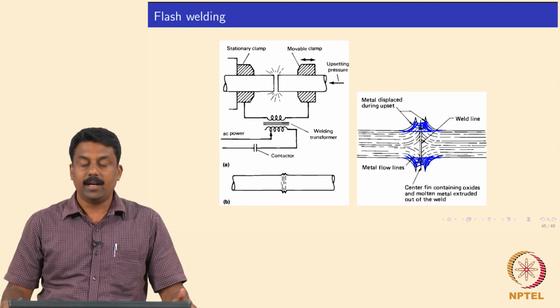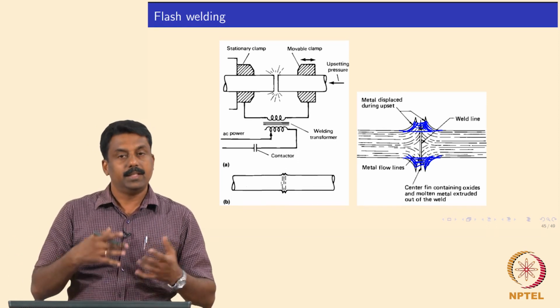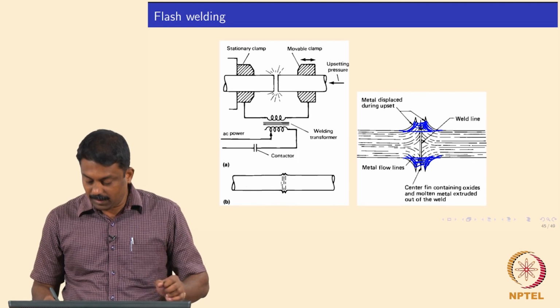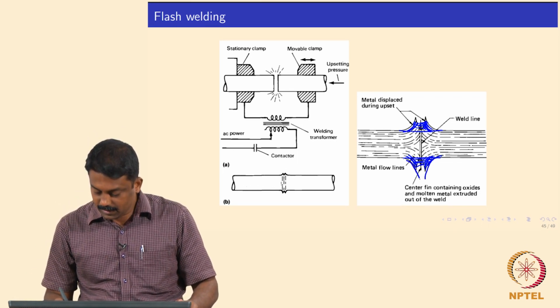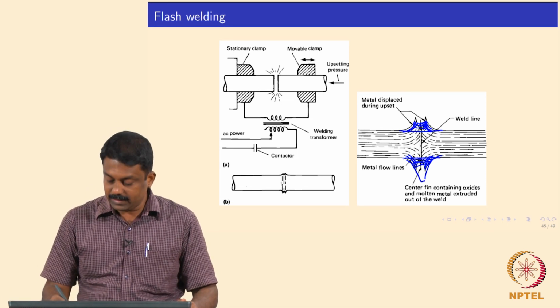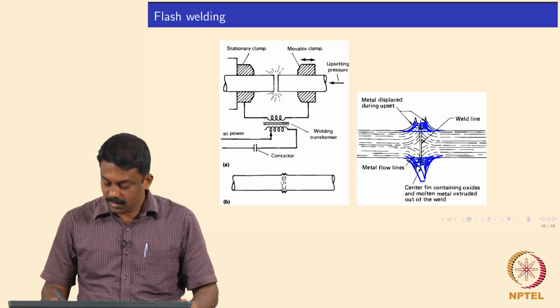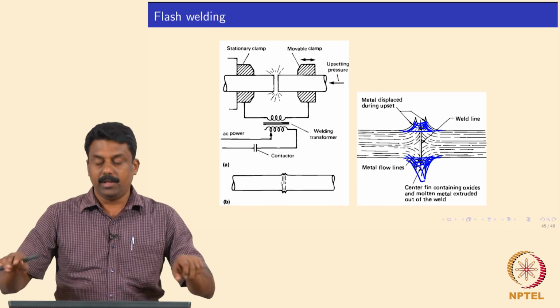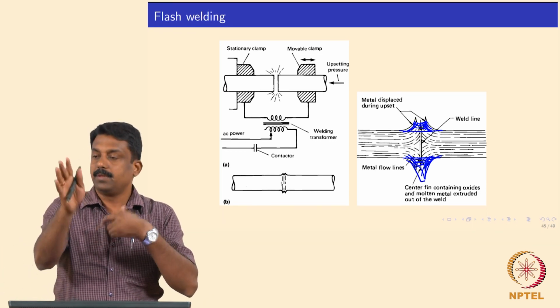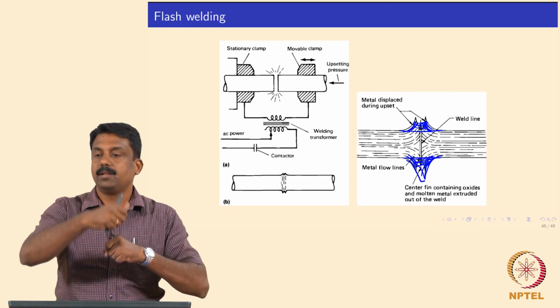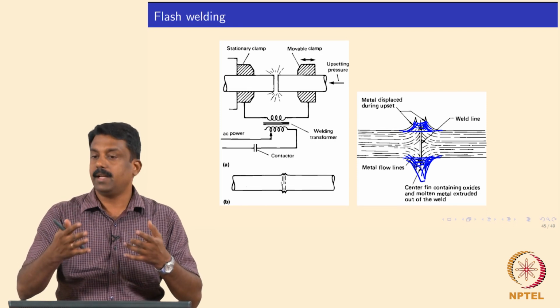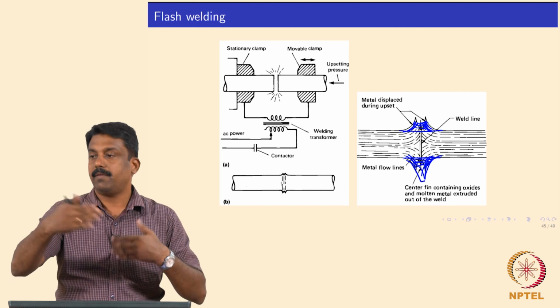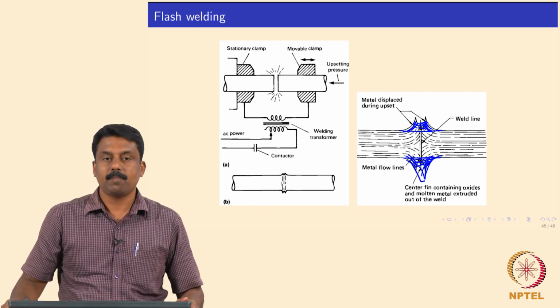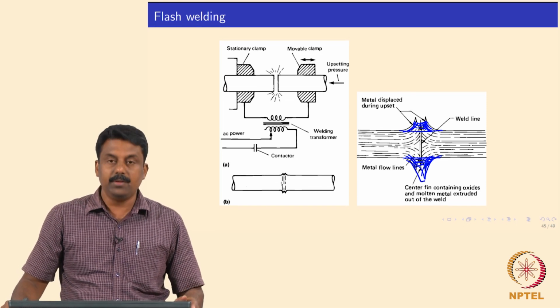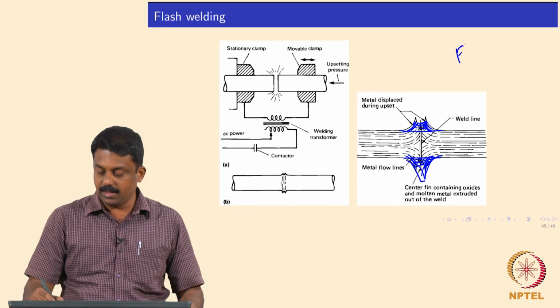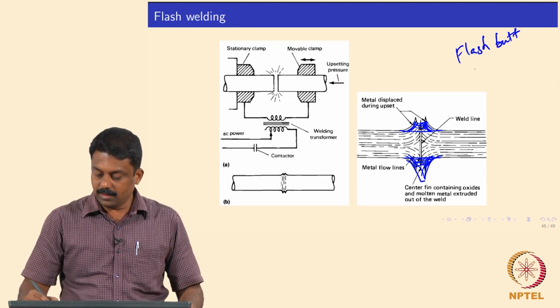Yes, it is clear. In resistance upset welding, generally the upsetting distance would take care of the contaminant issue. If you are upsetting for longer distances, obviously you also increase the flash distance. So whatever was there before welding would be pushed outside. If the upsetting distance is higher, you will end up sending the interface which was there before welding outwards. So whatever contamination was there, if you did not clean it properly, would be sent into the flash and you can machine it off subsequently. Yes, it is clear, good. Any questions on these two processes? You should always see the difference between flash butt and resistance upset welding.